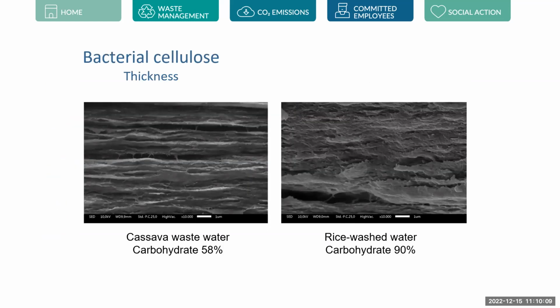Okay, this is the thickness of the bacterial cellulose produced from different sources of agro-industrial waste. The left one is the bacterial cellulose with carbohydrate content of 58%, produced in cassava wastewater. And the right one has a carbohydrate content of 90%, obtained from rice wastewater for bacterial cellulose production. Here we can see that the thickness of the bacterial cellulose is different. The thickness is really different. The left side is thinner and the right side is thicker, based on the carbohydrate content in the medium. Next, please.